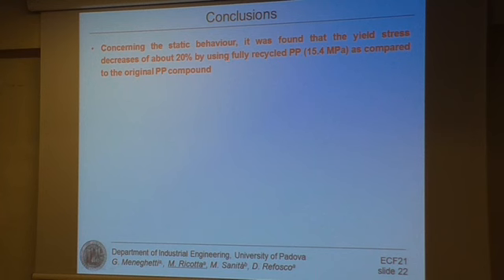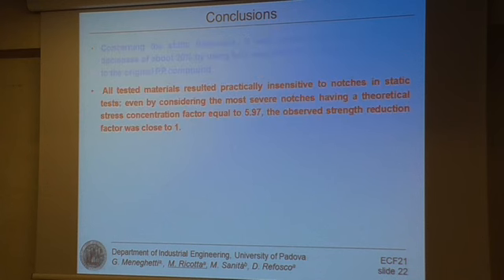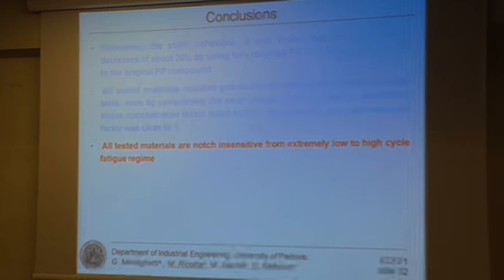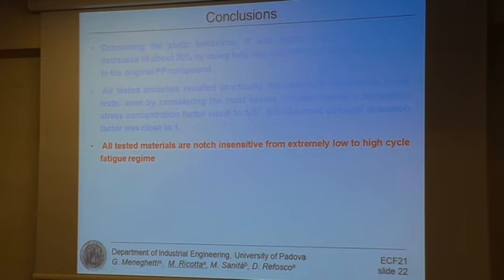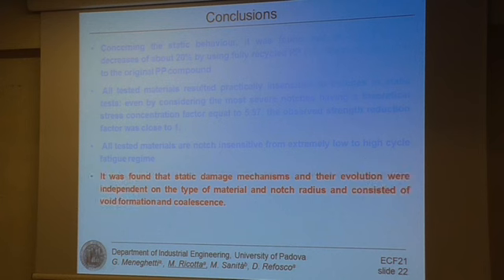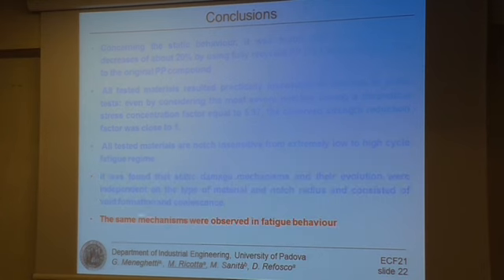Therefore, to conclude. Concerning the static behavior, it was found that the yield stress decreases of about 20% by using fully recycled polypropylene compound with respect to the original polypropylene compound. All tested materials resulted practically insensitive to notching in static tests. These results were also confirmed in the case of fatigue load from low cycle to high cycle fatigue regime. And finally, it was found that static damage mechanisms and their evolution were independent of the type of material and notch radius. They consisted of void formation and coalescence, and the same mechanisms were observed also in the case of fatigue behavior.